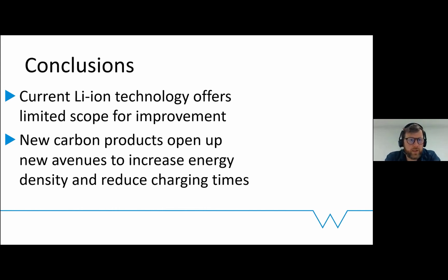One comment that I make, and Terence and I have been discussing, is that it seems to be with these additives more along the lines of the carbon nanotubes than the graphene. The graphene seems not to have the same level of confidence in terms of comparing apples with apples and what's a drop-in technology. It feels the carbon nanotube is that bit more predictable at the moment in terms of processing. And it just feels like somewhat of a gap for a good graphene offering in this area, which would be interesting to look at. But you can definitely see the advantages that come from it. Hopefully you can see the advantages in my brief presentation here.